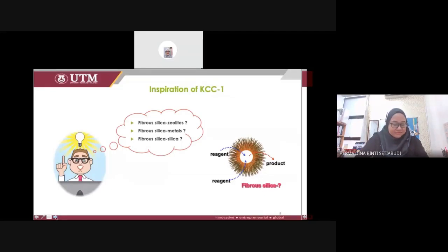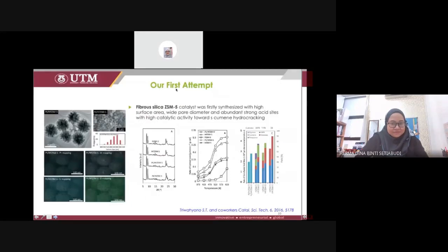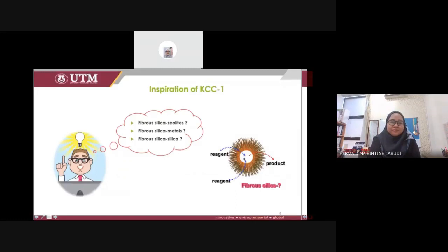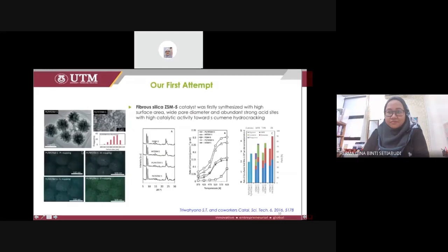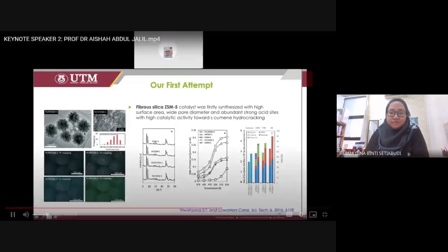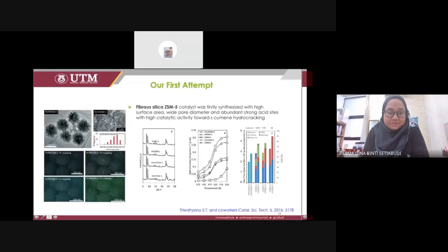So from this KCC1, our first attempt is to synthesize the fibrous silica ZSM5. Okay, so we tried to replace the silica inside in the core with the ZSM5 seed, and then we succeeded to synthesize that catalyst. As you can see, the structure maybe is not like the KCC1, the fibrous one, but still in the fibrous morphology form. And the particle size is quite big, average 400 nanometers. And then, as you can see here, this is the mapping for the ZSM5 catalyst loaded with Pt.